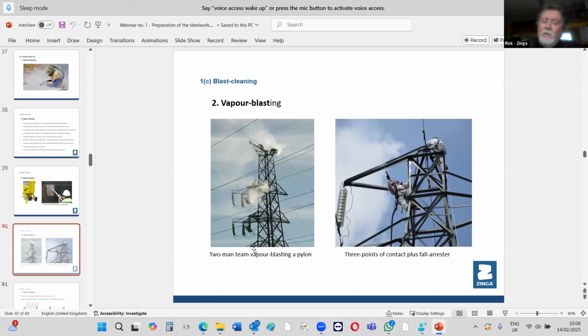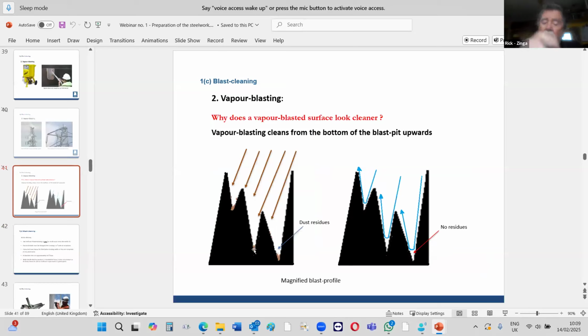And when you're blasting dry, you won't see with your eye, but under very strong magnification, you can see dust residues in the bottom of your blast profiles, right at the very bottom. When you vapor blast, it's a different physics involved. As you're striking the surface with the abrasive, the water is coming around the abrasive at the same time, and it's continually scouring the surface.